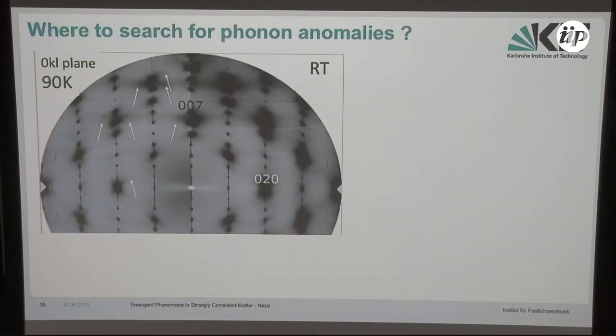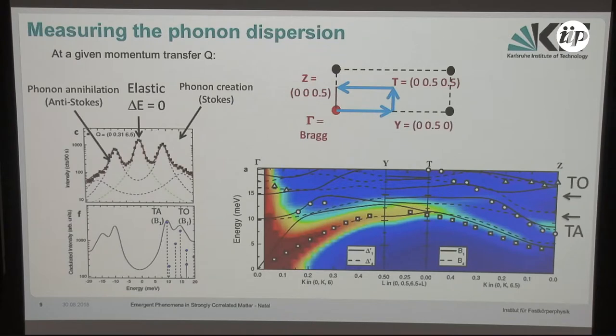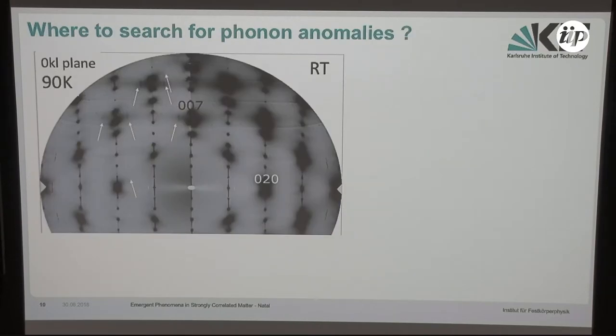Okay, so the question is really, in YBCO 7 you have 13 atoms, which gives you 39 phonon branches, and you're not going to study these 39 phonon branches one after the other to find out which phonon might eventually be anomalous. Normally, when you know which phonon you want to look at, you calculate the structure factor and find out which is the best Brillouin zone to work in. Here we did the opposite.